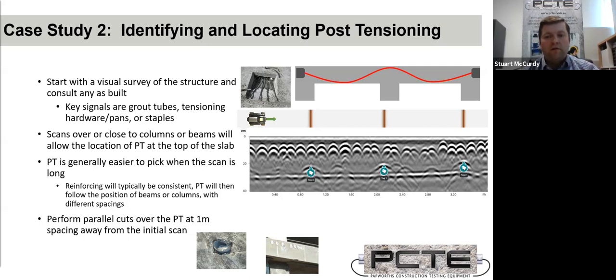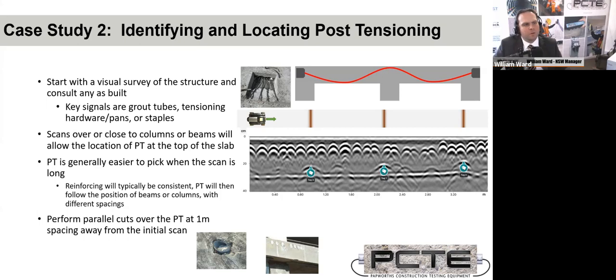With newer GPR systems allowing us to go deeper to 700 mil, if we did start mid-span, we would still expect to pick up the post-tensioning, but it's going to be a stronger reflection if it's closer to the surface. So this is still a good method to follow. One of the universal rules of any kind of NDT work is just because you haven't found something you expect doesn't mean it's not there. It means that it may not have been found by your hardware.